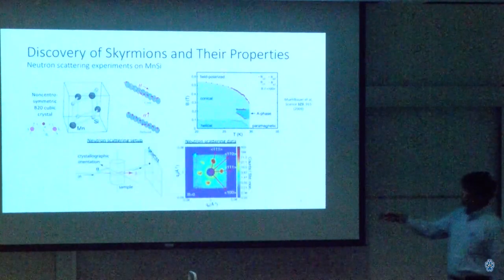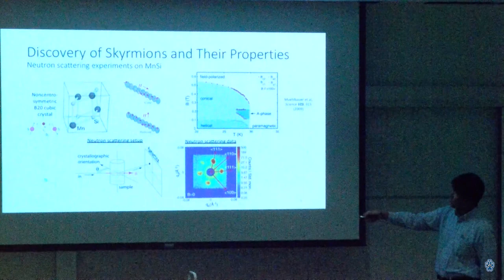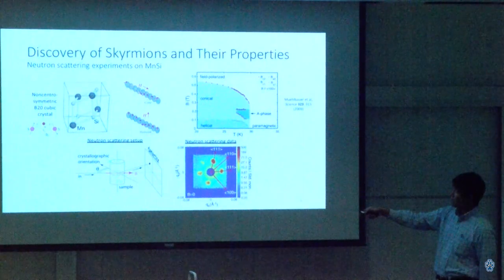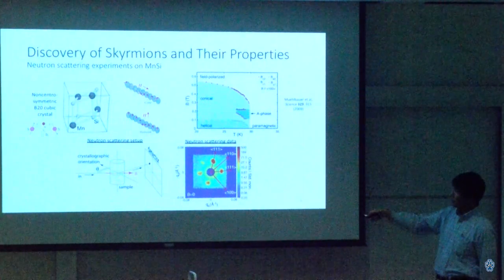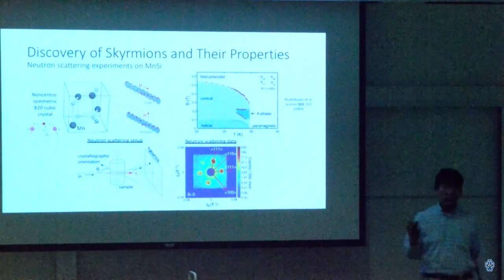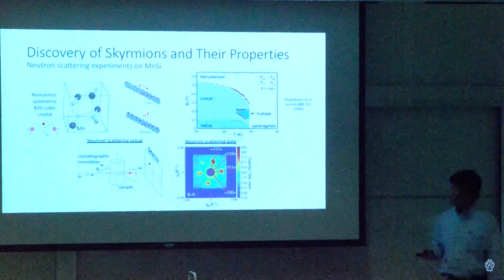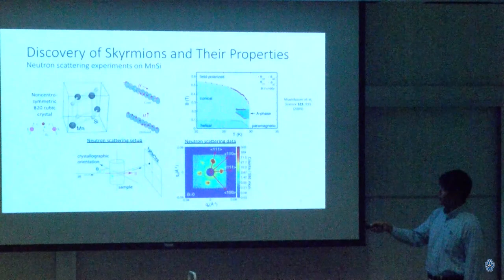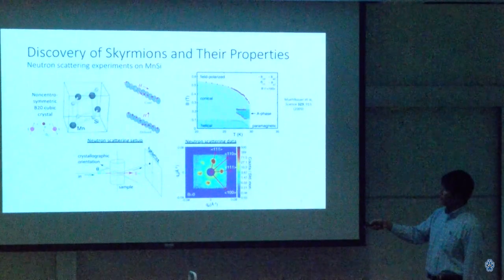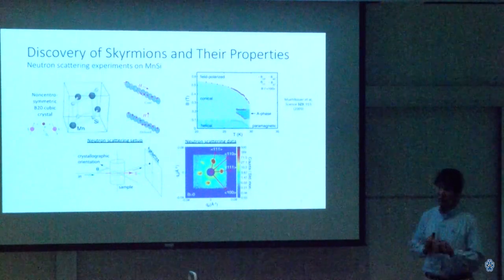That's the exact same kind of reasoning that they used. So this is a neutron diffraction pattern. And here's a schematic of their experiment. They have a cylindrical crystal of manganese silicide, and they have neutrons coming in from left to right. They're applying a magnetic field on the sample, and they're having the neutrons pass through the crystal and then diffract.